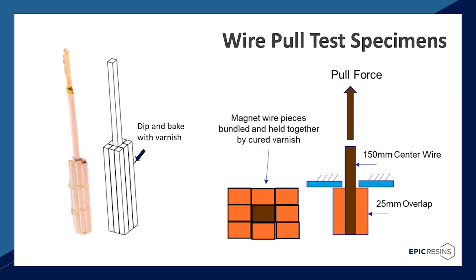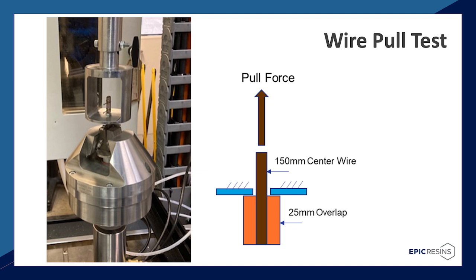This test is conducted by first constructing this wire bundle, followed by an insulation process that will mimic the manufacturing process. Once cured, the bundle is exposed to 2 different environments: elevated temperature exposure immersed in ATF and elevated temperature exposure to ATF vapor. Samples that were conditioned at each of these temperatures are then evaluated at different time intervals: 500, 1000, 1500, and 2000 hours. The integrity of the adhesion is then tested by the fixture in the illustration. This fixture measures the force required to break the center wire free, which mimics the wire in the slot.